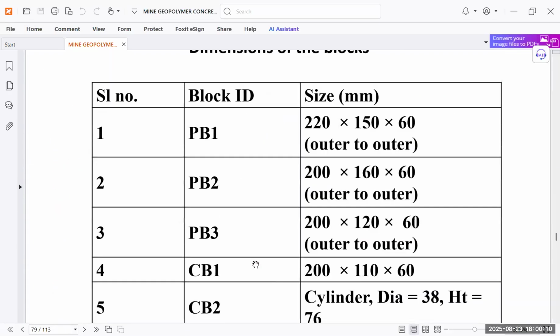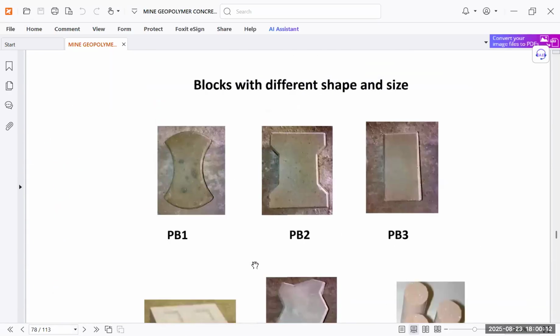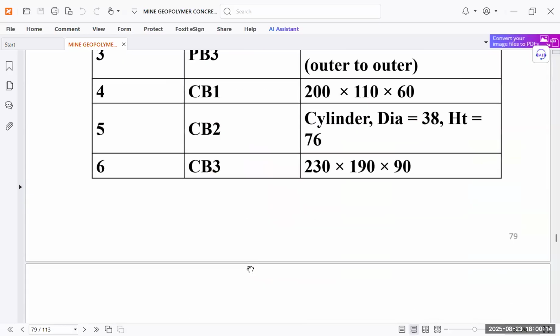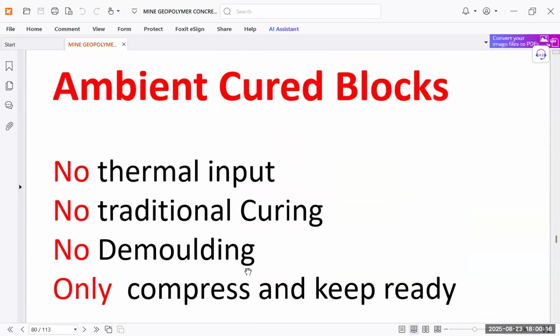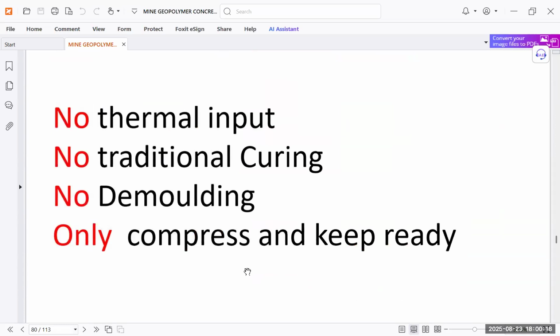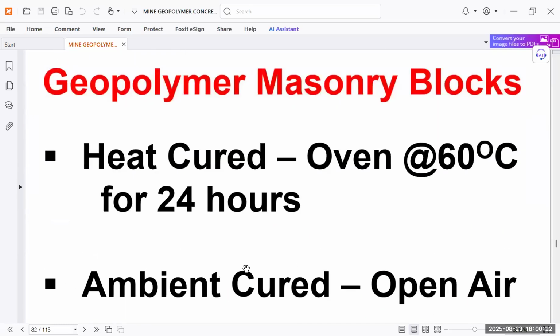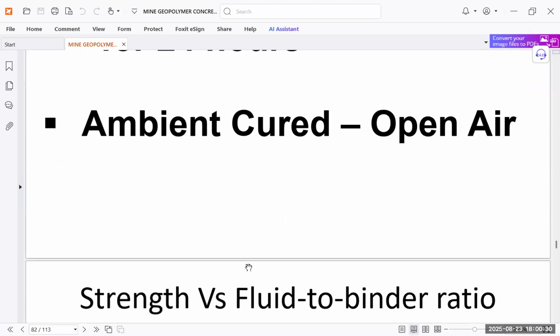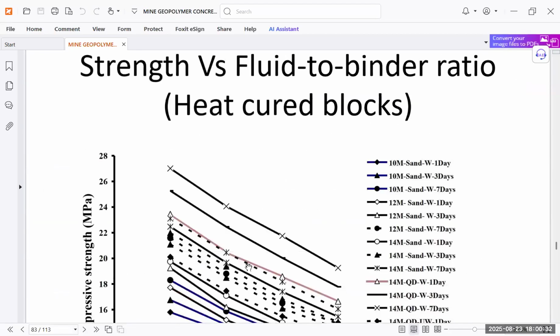So ambient curing is there. These are its different shapes, and their curing is ambient curing. No thermal input is there, no traditional curing is there, only compression treatment. These are the geopolymer masonry blocks. Compared to oven curing at 60 Celsius for 24 hours, here we use ambient curing in open air, but for strength versus fluid to binder ratio we are getting the same.